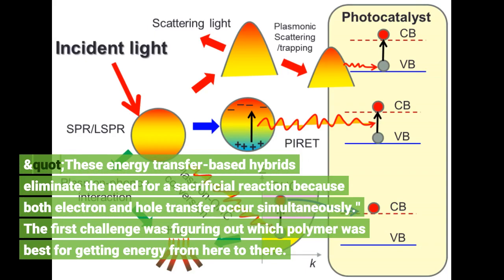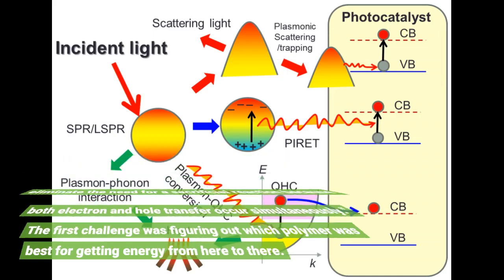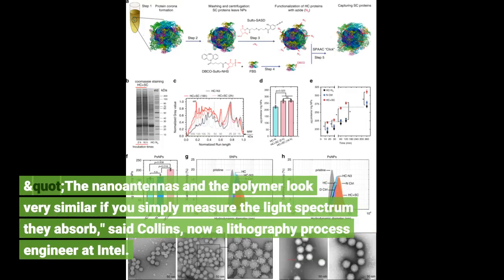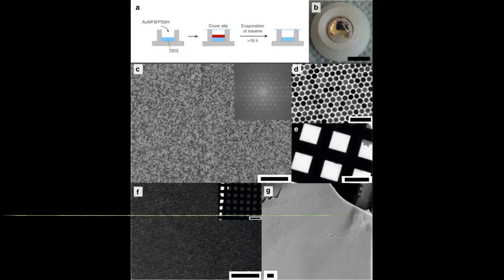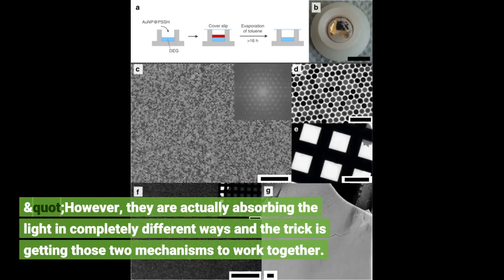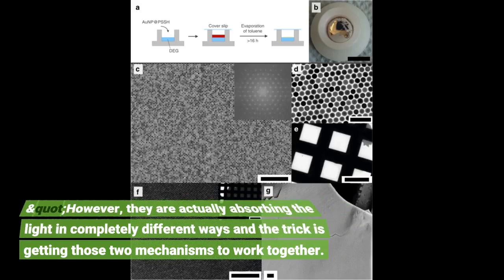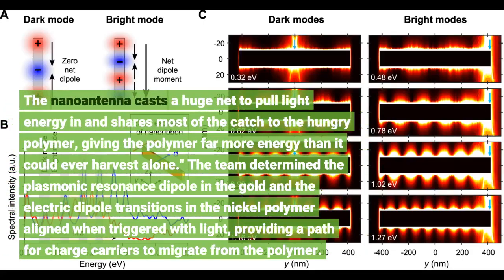The first challenge was figuring out which polymer was best for getting energy from here to there. The nanoantennas and the polymer look very similar if you simply measure the light spectrum they absorb, said Collins, now a lithography process engineer at Intel. However, they are actually absorbing the light in completely different ways, and the trick is getting those two mechanisms to work together. The nanoantenna casts a huge net to pull light energy in and shares most of the catch to the hungry polymer, giving the polymer far more energy than it could ever harvest alone.